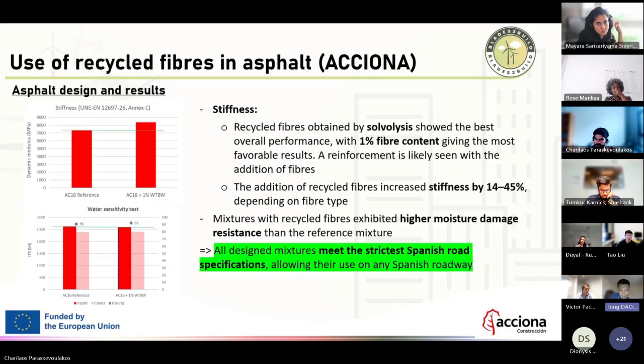And this increase is very important, about 14 to 45% depending on the fibers, because as I told before, they tried 2 types of fibers from pyrolysis or solvolysis processes with different percentages. Here they don't put the details, but the conclusions showed from 14 to 45. Okay. And then in terms of durability, they also tried the water sensitivity test.